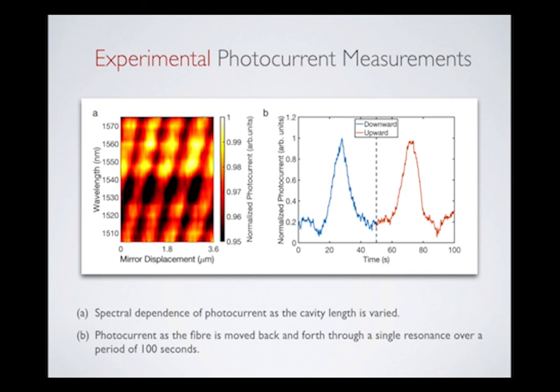The spectral response of the cavity-based photodetector is shown in Figure A. The cavity modes are clearly apparent, providing much greater photocurrent than in the case of off-resonance, due to resonance scattering from the grating. This scheme also enables direct control over the detection wavelength, as the resonance conditions can be dynamically tuned. This is highlighted in Figure A, as the peak response is mechanically tuned over the spectral range of the laser by altering the Z position of the top mirror. The photocurrent from this resonance system is roughly 5 times greater compared to the off-resonance condition.